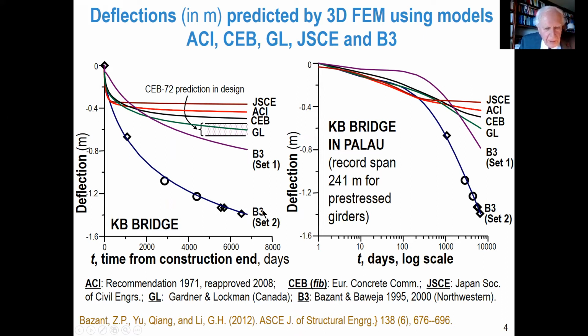It was predicted by the B3 model accurately, which we developed at that time, but it was grossly underpredicted by codes applicable at the time, JSCE, ACI, CEB, about 30 or 20% of the actual value. The same is plotted here in the logarithmic scale. You see again the straight line extension at the end.